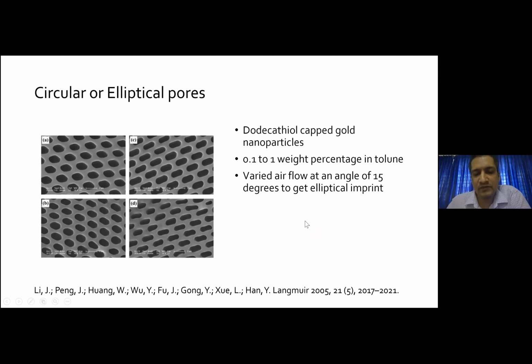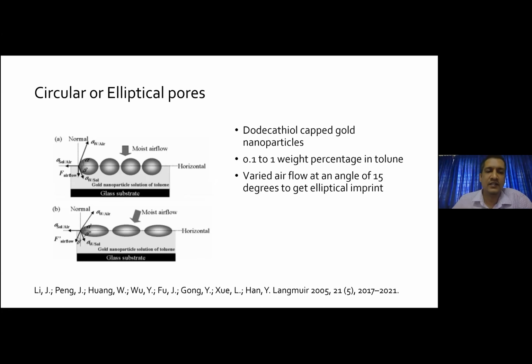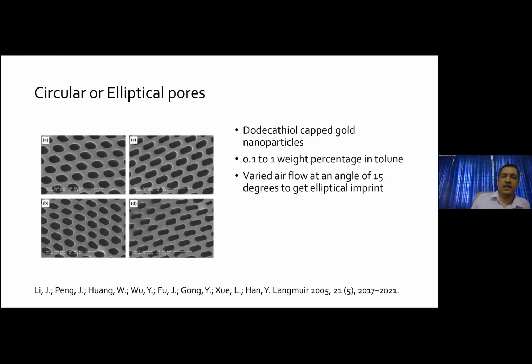So here also the experiment is done by carefully designing the experimental setup. What they did is they took dodecanethiol-capped gold nanoparticles in toluene, and they allowed the air to flow at an angle of 15 degrees instead of perpendicular. They slightly tilted the airflow and varied the rate of airflow, and by modulating the angle and the airflow, they are able to show that it is possible to get an elliptical pattern.